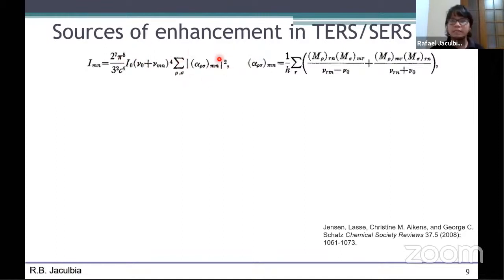So this term is the so-called Raman tensor, or the Raman polarizability tensor. The important point is that this term is the energy of the vibrational mode, and this term is the energy of the incident light. So basically, from this equation, it's easy to see that when the energy of the incident light is equal to the energy of the vibrational mode, then this term is maximum and the Raman signal is very large. In such a case, this is the so-called resonance Raman effect.